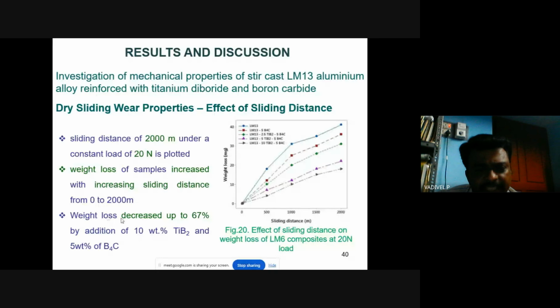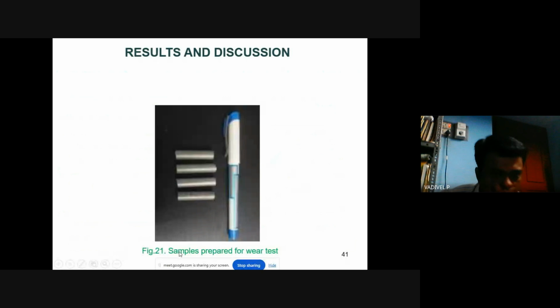The weight loss decreased by up to 67% by adding 10 weight percentage of TiB2 and 5 weight percentage of boron carbide. In this material, the weight loss stops at some particular point, and after that the weight loss is very negligible. These are the samples which are prepared for the wear test.